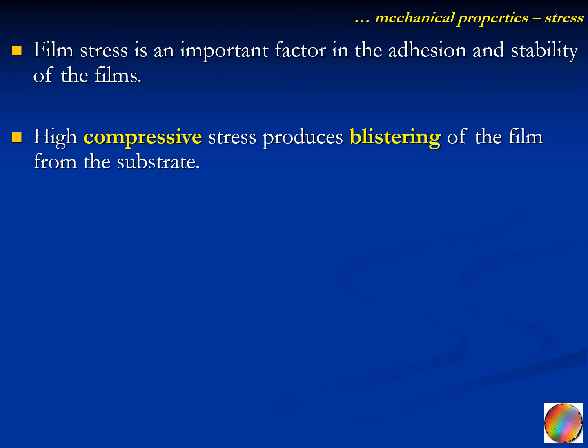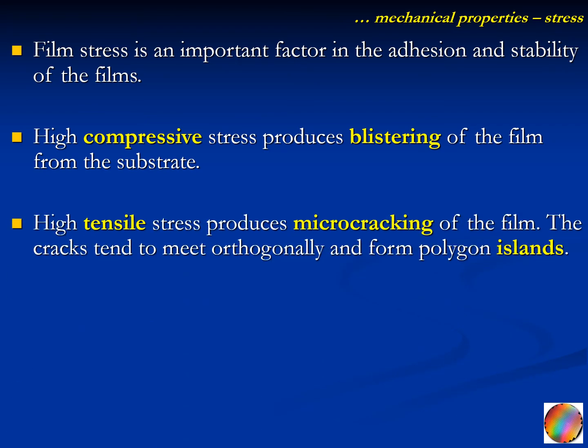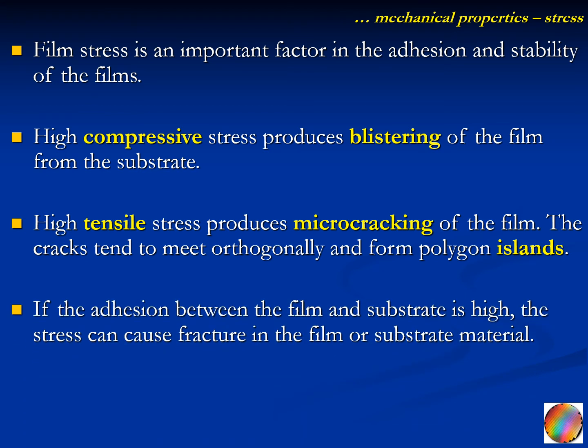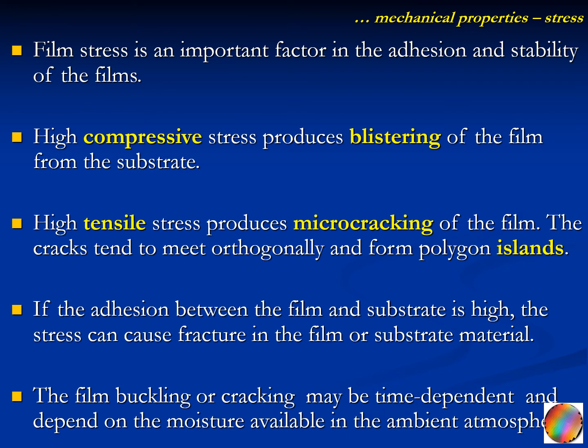High compressive stress produces blistering of the film from the substrate, removing the film from the substrate. High tensile stress produces micro cracking of the film, and the cracks tend to meet orthogonally and form polygon islands. If the adhesion between the film and the substrate is high, the stress can cause fracture in the film or substrate material. The film buckling or cracking may be time dependent and depends on the moisture available in the ambient atmosphere.